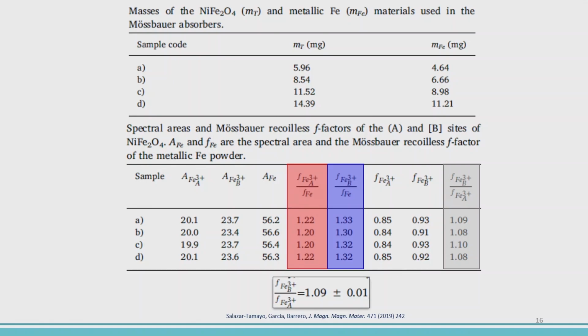And moreover, the relative F factors for the B to the A sites are not equal to that of magnetite. I have found that this is also another common error in the literature. Most papers, for every ferrite, doesn't matter which ferrite it is, always assume that this coefficient is equal to that of magnetite. It's not equal to that of magnetite, at least this is what we found for the samples. Of course, this ranges from sample to sample.